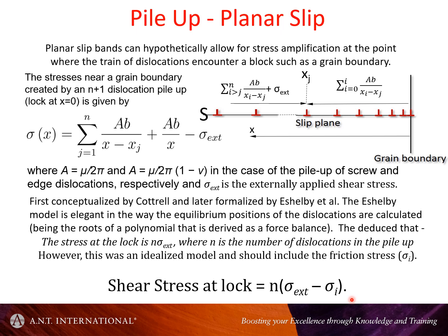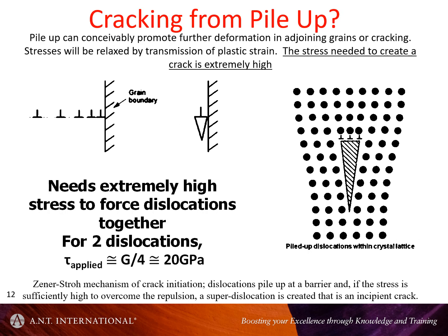So this concept was first conceptualized by Alan Cottrell and later formalized by Eshelby. Eshelby and company had a very nice, elegant study to show that these dislocations, where their equilibrium position, if you like, depending on the applied stress and the number of dislocations, can be reduced to a polynomial, and where the dislocations are their positions, where basically zero or stable minimum in the energies, the minima are roots of the polynomial. It's kind of neat. Okay, so where does this take us?